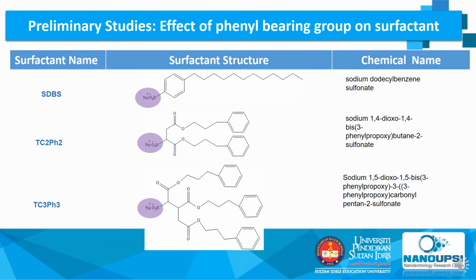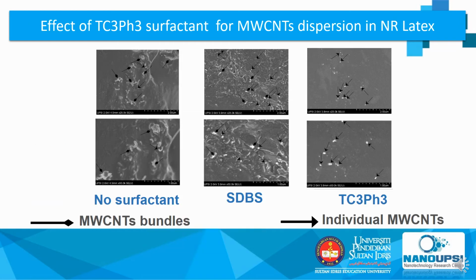So before we proceed with the experiment for graphene in natural rubber latex, we did some preliminary study using carbon nanotubes, where two different surfactants were synthesized by introducing a phenylpropoxy group in the surfactant chain of TC2PH2 and TC3PH3, and these synthesized surfactants were cross-compared with the commercially available SDBS. Interestingly, by introducing the phenylpropoxy group in the surfactant chain, we were able to stabilize the carbon nanotubes in the natural rubber